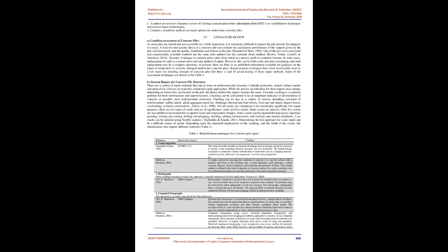Since the concrete has an insignificant tensile strength, cracks happen as the volume changes under temperature and humidity variations. However, cracks might occur under overloading, reinforcement corrosion, and structural settlements. Even if the cracks are not large, they are indicators of early structural deterioration, surrounded by salty water with harmful material accelerating the damaging process.